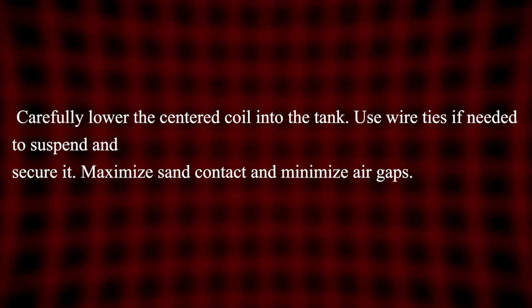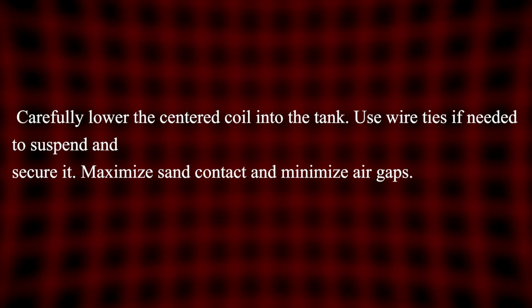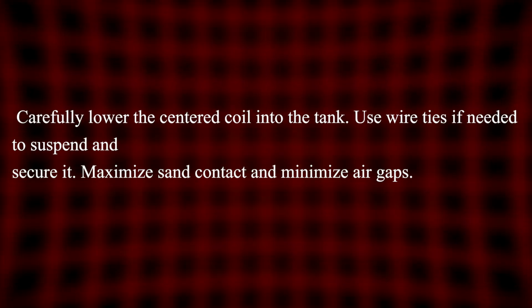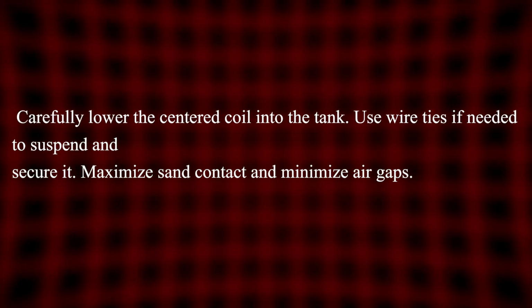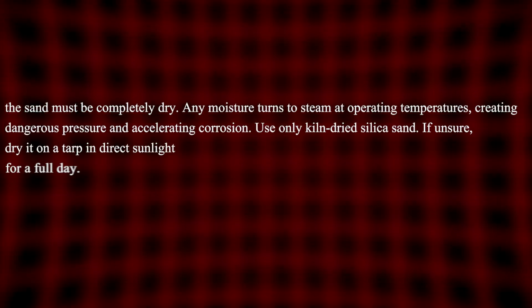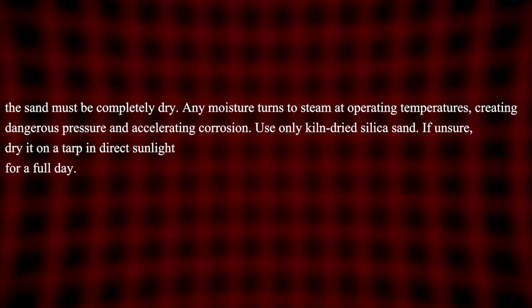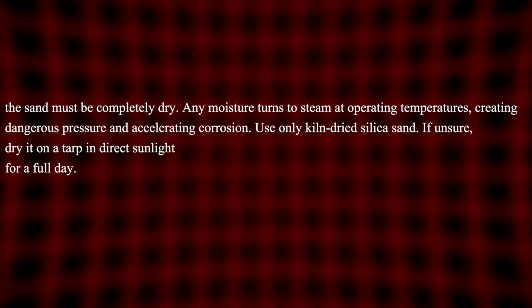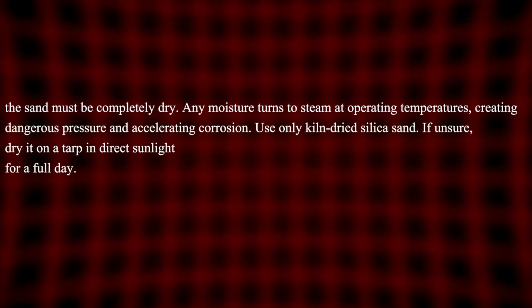Step 5. Carefully lower the centered coil into the tank. Use wire ties if needed to suspend and secure it. Maximize sand contact and minimize air gaps. Filling the tank follows 2 unbreakable rules. First, the sand must be completely dry. Any moisture turns to steam at operating temperatures, creating dangerous pressure and accelerating corrosion.